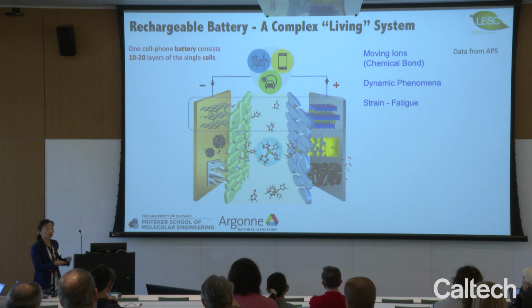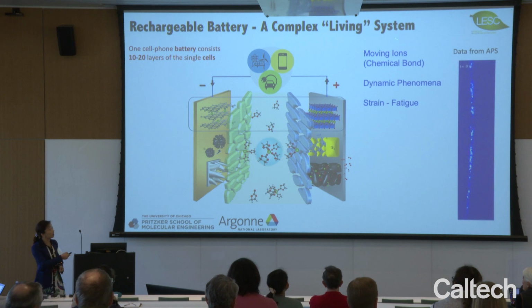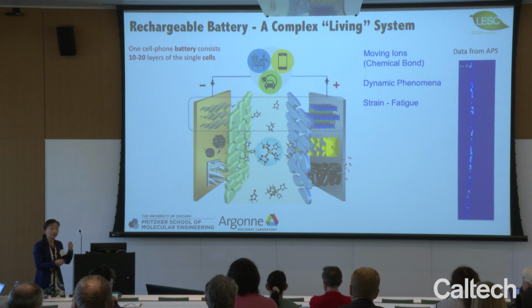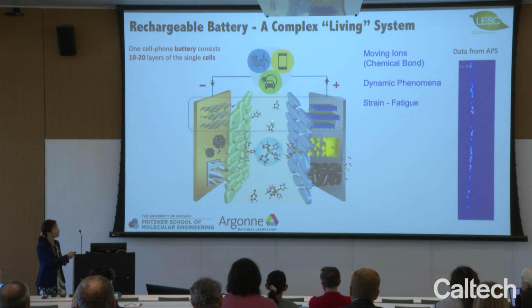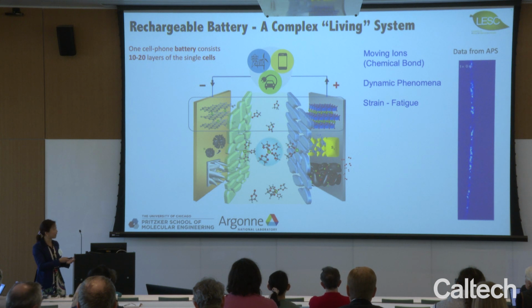And that made the job very challenging for material scientists, because every time we shuffle lithium from one electrode to the other, you are breaking the chemical bond and then reforming the bonds. And during this process right now, unfortunately, we have to use a liquid electrolyte, okay? And this liquid electrolyte actually is thermodynamically unstable with both electrodes at either very reductive potential or very oxidative potential. And this is where all the weak links start: we have the flammability problems, we have the degradation.